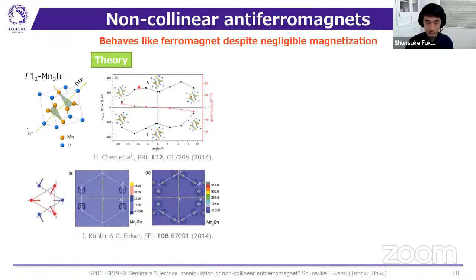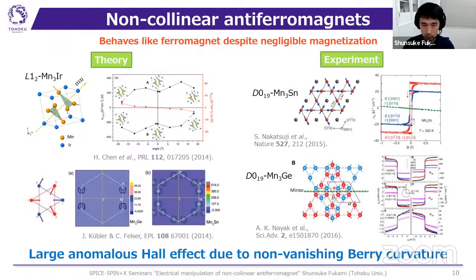And theoretically, Professor Allan MacDonald's team and Claudia Felser's team predicted that a large anomalous Hall effect would be observed due to the non-vanishing Berry curvatures in manganese-3 iridium, manganese-3 germanium, or manganese-3 tin. And indeed, in 2015, Professor Nakatsuji and Stuart Parkin's team observed the large anomalous Hall effect in manganese-3 tin and manganese-3 germanium. So the large anomalous Hall effect is observed due to the non-vanishing Berry curvatures.